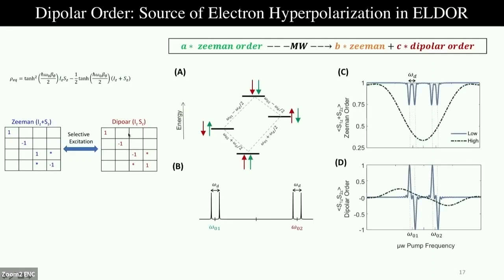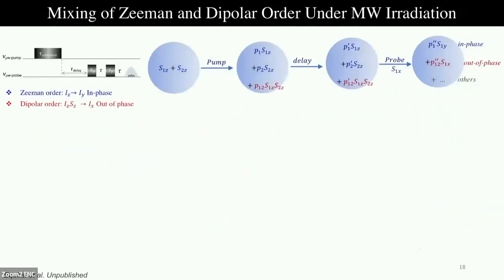And in this numerically simulated spectrum, you can see for a coupled spin system, if we do a selective saturation, then we saturate the Zeeman order, but simultaneously we are creating the dipolar order or two spin order. And if we saturate with higher microwave power, the two humps get more separated, but it's created. So selective saturation can lead to the creation of two spin order or dipolar order.